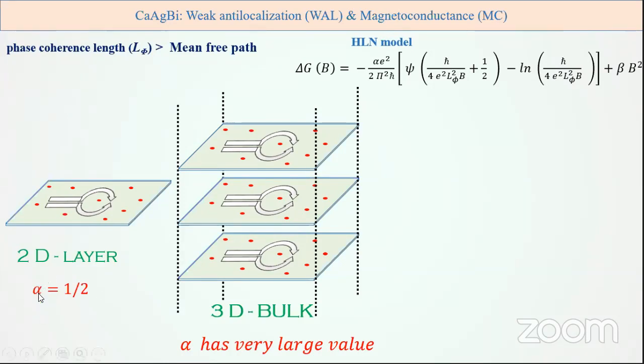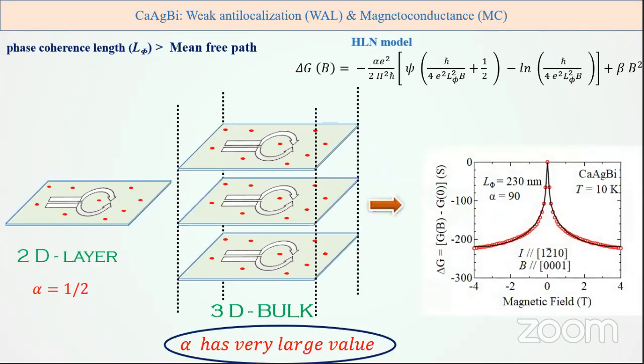For one conduction channel, the alpha value in the Hikami-Larkin-Nagaoka model should be half. But for a bulk system, as there are a large number of conduction channels, this alpha value should be very high. As I told you, this weak magnetoconductance data we can fit with the HLN model, and from there we can calculate L_phi, the phase coherence length, as well as the alpha value. The observed L_phi value is almost 230 nanometers, and the alpha value is quite large, which concludes that our system has a large number of conduction channels.